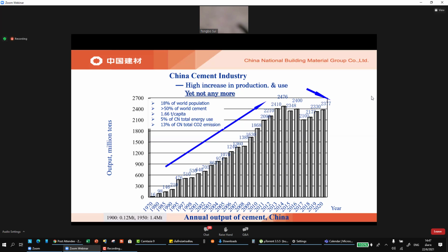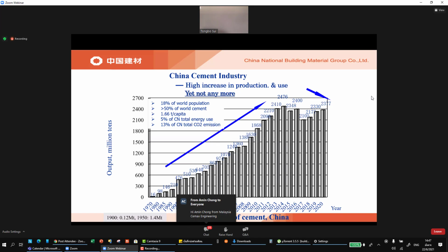But even so, when we look at the figures of per capita yearly consumption of cement, we are still very high, 1.3 tons per capita. And also in terms of CO2 emission, the cement industry accounts for around 13% of CO2 in China.